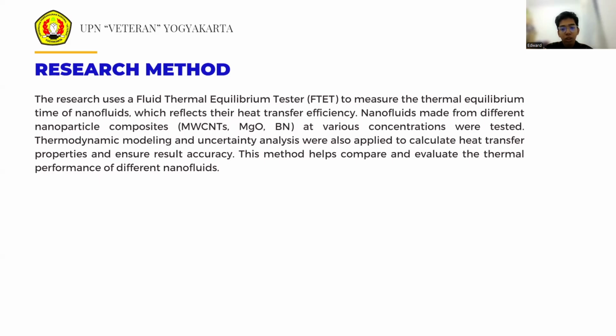The temperature in both cylinders equalized. The time taken to reach this equilibrium, the thermal equilibrium time, was calculated and used as an indicator of the nanofluid heat transfer efficiency. Each test was repeated under controlled conditions to ensure repeatability, with the system allowed to cool to room temperature between tests to maintain consistent conditions.